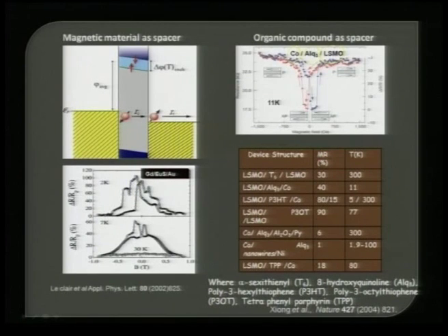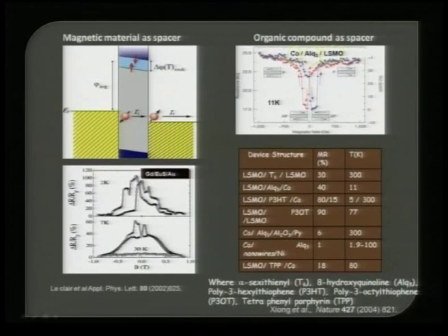because of the non-magnetic layer. Why? Because if you are using a metal as the non-magnetic layer, or a heavier metal ion, then there will be spin orbit coupling that is contributing. As a result, there will be spin orbit coupling happening as it goes from here to here. So it is better for us to replace this metal with an organic layer, because the spin relaxation times are of a very large scale, since there is no metal in organic compounds. So the electron can take its own time to carry its spin memory from here to here without any scattering.